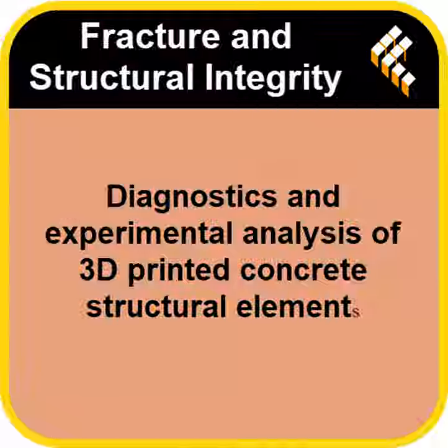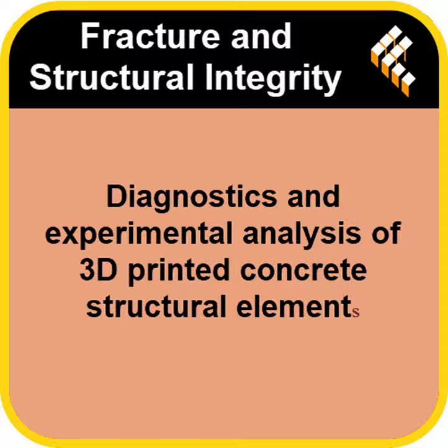And did it? It did, surprisingly well. The FEM analysis matched the initial stiffness, the overall load deflection shape, and the predicted peak loads were right in the ballpark. How close? The model predicted between 5.8 and 7.2 kilonewtons, and the experiments recorded between 6.2 and 7.5. So very close. What's really valuable there, I think, is how the model explained the two different types of failure.